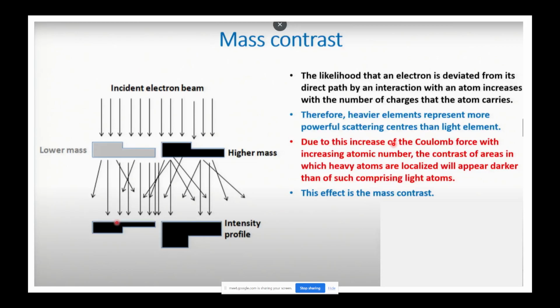So here, what is the mass contrast? Here you can see the incident electron beam is coming. Here you will have a lower mass sample. This is your higher mass. When the incident beam is interacting with the lower mass, it won't deviate much or scatter very highly. But when it is interacting with the higher mass, because of its higher mass, it will scatter much. So that's why the intensity profile for the lower mass is different than for the higher mass, isn't it?